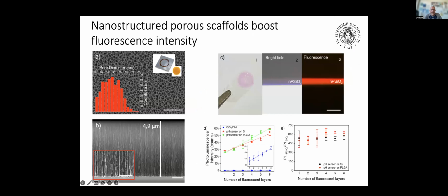Here you see some of the fabrication results, the membrane we detach, and in this picture you see the PLGA foil with the porous silicon membrane functionalized with the fluorescent polyelectrolyte. The nice thing of using porous silicon is that we can leverage the increase of the specific surface of this material. In fact, we can increase the photoluminescence intensity by about 500 times compared to the flat substrate, which is important for in vivo application, because we need to go through skin. So what we want to do is measure the change in the fluorescence through skin, and this is very useful for that.